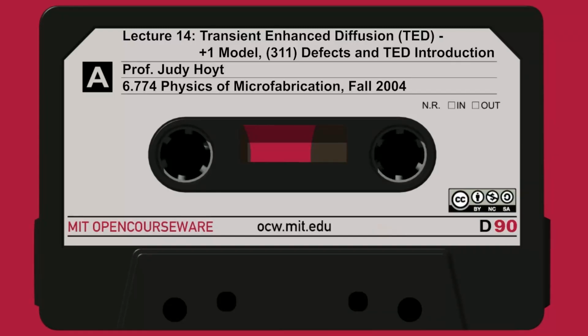Okay, so let me just summarize what we've said about ion implant and TED. Ion implant is the dominant method for putting dopants in. We talked about range statistics that we can calculate using simple distributions. We talked about Pearson 4 in amorphous targets, how it works very well. Ion channeling has to be modeled by something more complex and complete like Monte Carlo. Next time I'll show you some ion channeling profiles and how they're fit by dual Pearson. We spent some time today talking about the +N model for residual implant damage. It tells you that you get roughly N excess interstitials per primary ion.